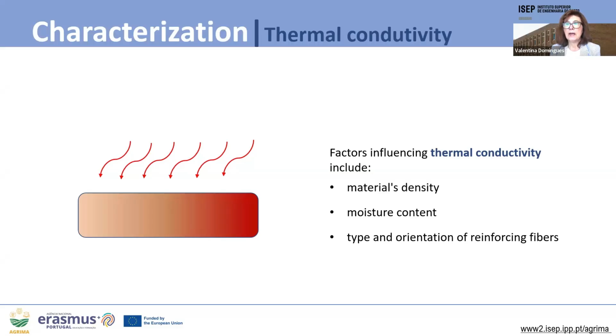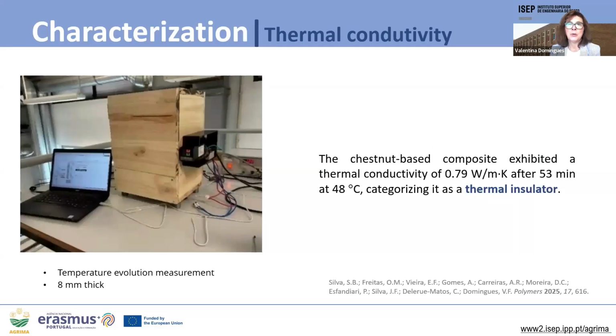The thermal conductivity of biocomposites is a crucial parameter that affects their suitability for various applications, particularly in insulation and energy-efficient designs. Factors influencing thermal conductivity in biocomposites include material density, moisture content, and type and orientation of reinforcing fibers. We use homemade equipment to evaluate thermal conductivity, and our chestnut-based composite exhibits a thermal conductivity of 0.79 watts per meter Kelvin after 53 minutes at 48 degrees, categorizing this biocomposite as a thermal insulator.